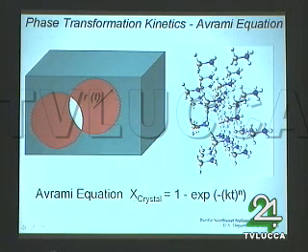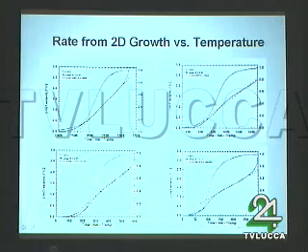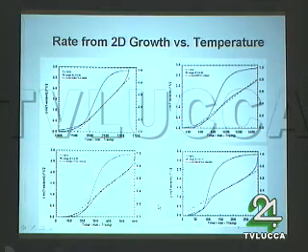And the Avrami equation for this crystal formation, for crystallization, it has both a rate constant in it for the reaction that you can do as a function of temperature, and this exponent here, n, which tells you something about the growth, whether it's 2-dimensional, 3-dimensional type of growth. So you can fit the kinetic data that we did by just integrating the amount of hydrogen that comes off, or heat, and get some information about the rate, and try and find out how this polymer is growing.